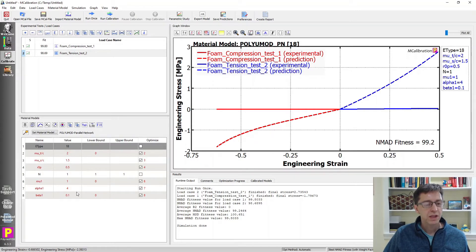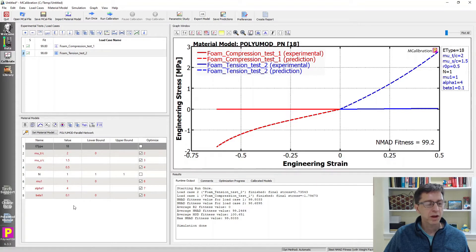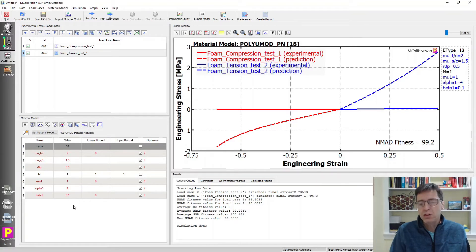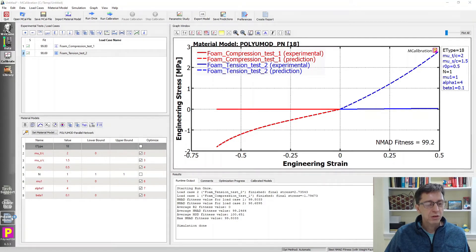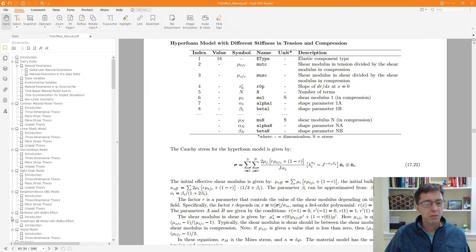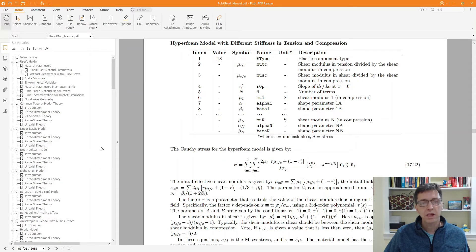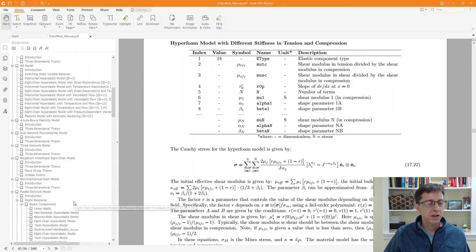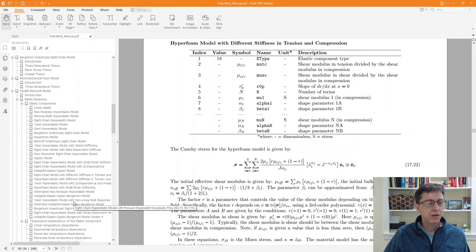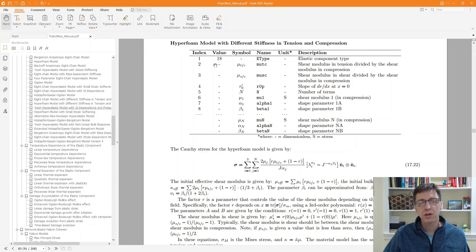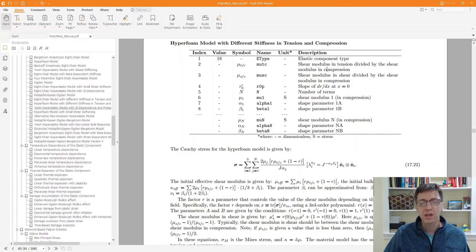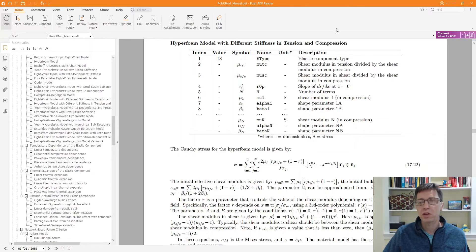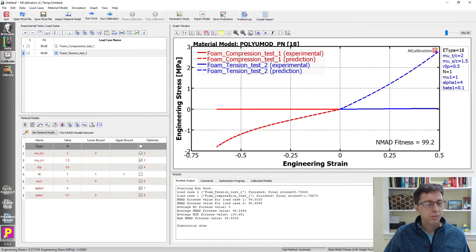If I run once before we think about this, we'll see what's going on. It looks like there is a slightly different slope between tension and compression. It's still way too stiff, we need to fix this. The parameters here you may not be familiar with. If you have a situation like this, well I don't know what this mu_tc thing is. You can look at what that means from the PolyUMod manual by clicking on that. It says that mu_tc is the shear modulus in tension divided by the shear modulus in compression, exactly what we're looking for.